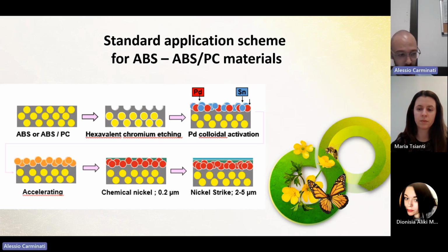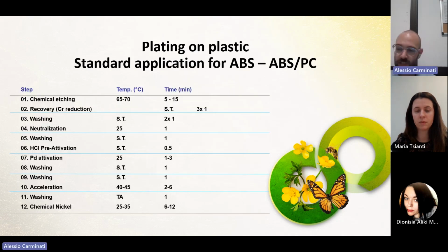So basically, the process involves a first step in which the surface is made capable of sustaining the metal plating at the end of the process. So we have an etching with hexavalent chromium that roughens the surface, and then an activation with a noble metal, with palladium, that will make the substrate capable of reaching the chemical nickel, the electroless nickel on it. So these are basically the steps involved and the type of parameters of a standard process.